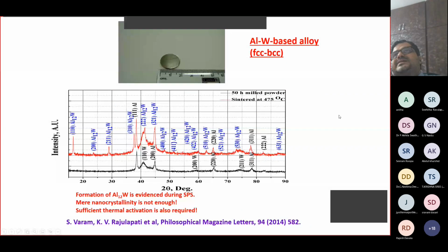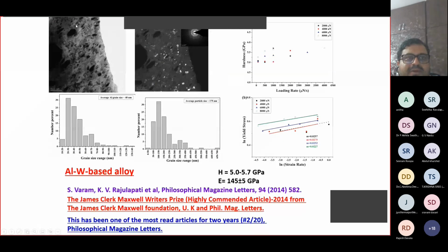So at a given grain size, lead is softer compared to aluminum, and also aluminum and lead both belong to the FCC structure. The other system that we have developed is the aluminum tungsten alloy, and this is the sample that we have here. After ball milling, we have the presence of both aluminum and tungsten. But after sintering at 475 degrees centigrade, we see a precipitation of an intermetallic called Al12W. And we published this work in Philosophical Magazine Letters. And these are the microstructural details from TEM. You have the presence of both aluminum and tungsten here. These are all the grain size and particle size statistics of aluminum and tungsten.